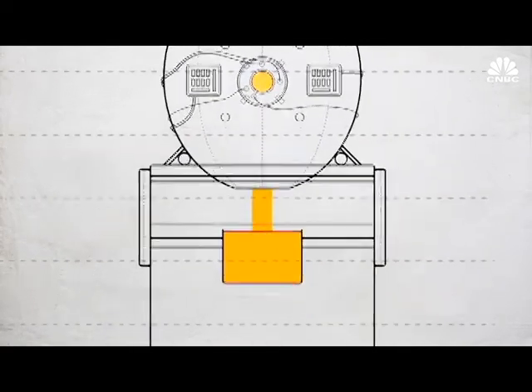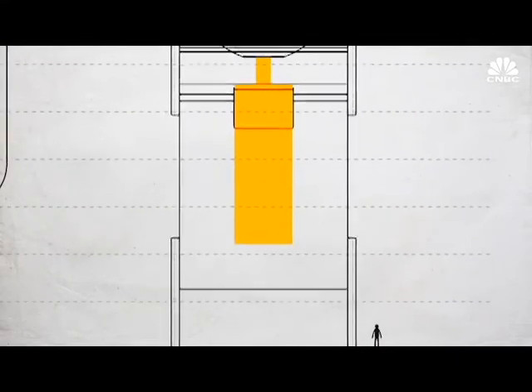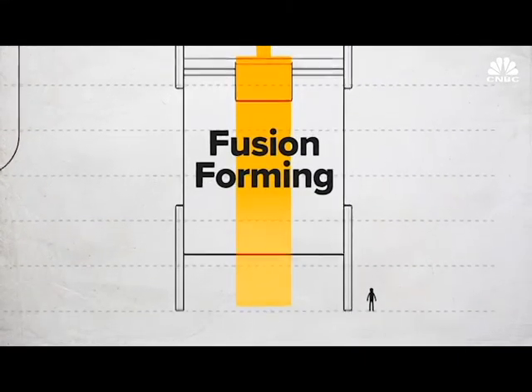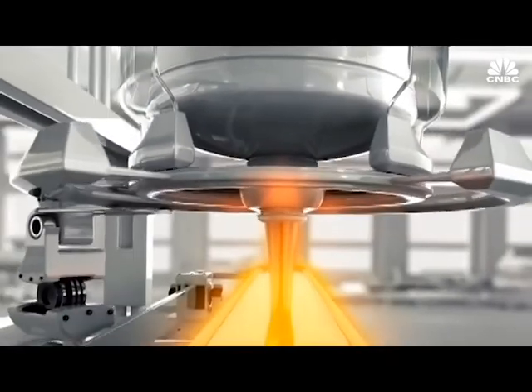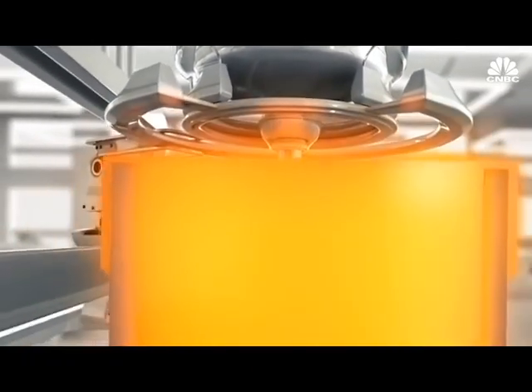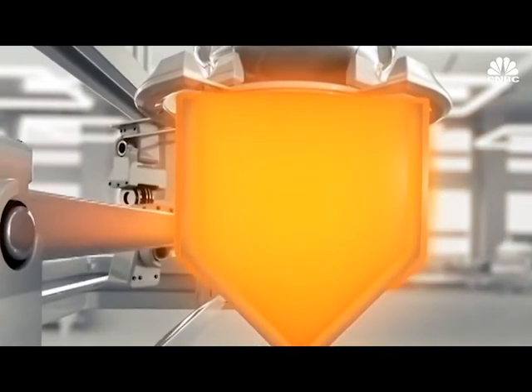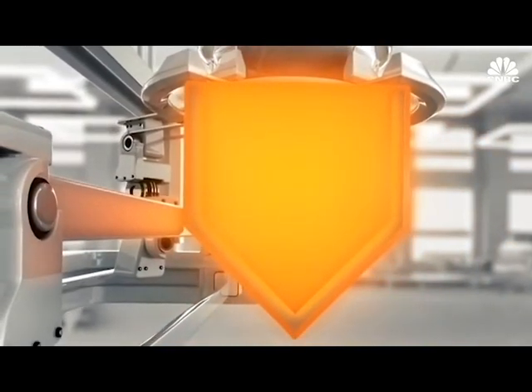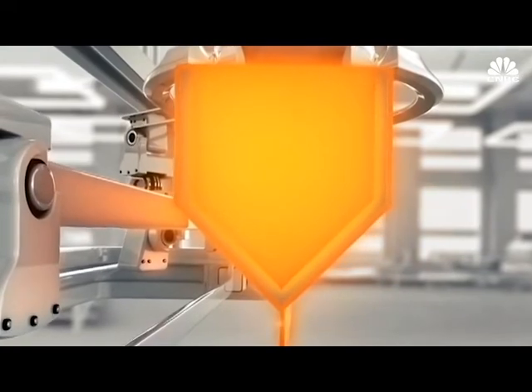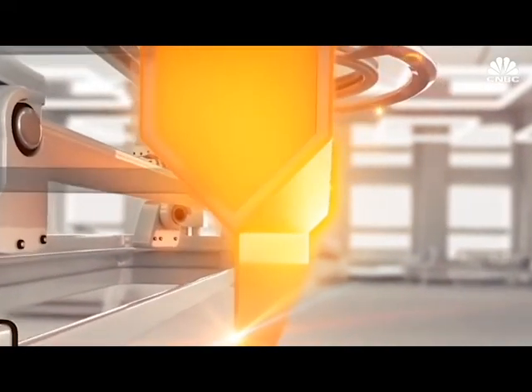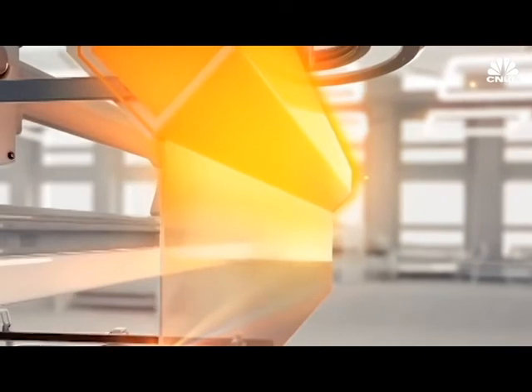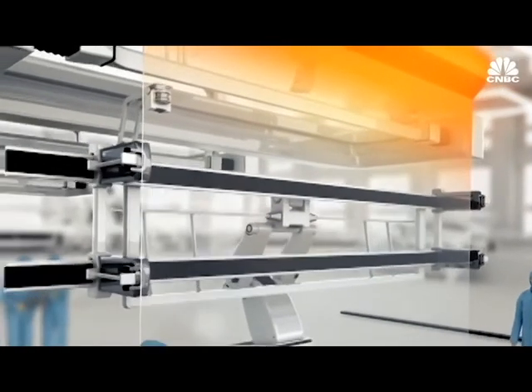The molten glass is fed into a trough called an isopipe, overfilling until the glass flows evenly over both sides. It then rejoins or fuses at the bottom, where it is drawn down to form a continuous sheet of flat glass that is so thin it is measured in microns. The glass is untouched by human hands or anything else that could introduce flaws into the surface. The raw materials are fine powders, silicon dioxide, for example sand, and limestone and sodium borate, mixed with other Corning secret recipe materials.